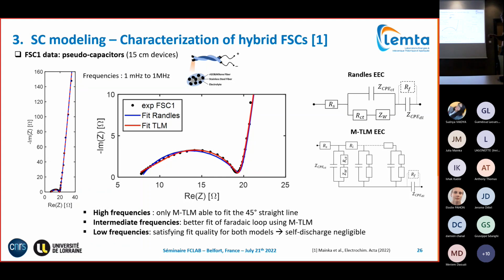But what we would obtain when connecting an additional inductance. So this was a very low inductance, and we compared connecting the inductance or not. Having an inductance, we would have a better fitting quality, but we would identify the same values for the other parameters. Physically, for me, connection of inductance only results in a better fitting curve, with the same conclusions that I showed you here. And again, I just remind you, the more parameters you have, the higher the probability of correlations between the parameters. In order to be sure, you want to keep the correlation between parameters as low as possible. Therefore, I skipped it.